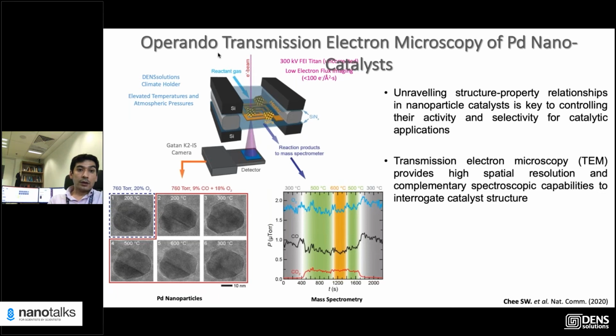So here, this is a basic setup for the Climate. You have a reactant gas or a mixture of reactant gases coming in. You deposit your nanoparticles. In this case, we deposited the palladium nanoparticles, and you start flowing the gas. You start recording images. At the same time, the output of your cell is connected to a mass spec, and then you can monitor what's happening with the reactants and the products, and you can control the temperature. And that's exactly what we did. So we combined this mass spec with the TEM to see what happens to the nanoparticles under the reaction conditions.